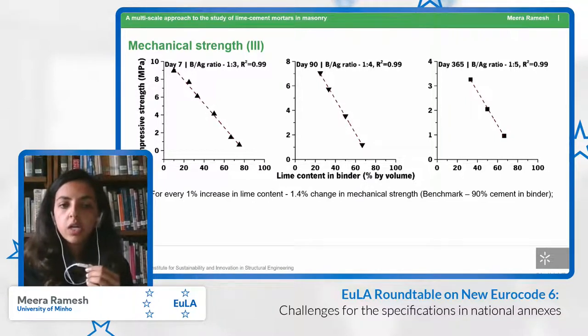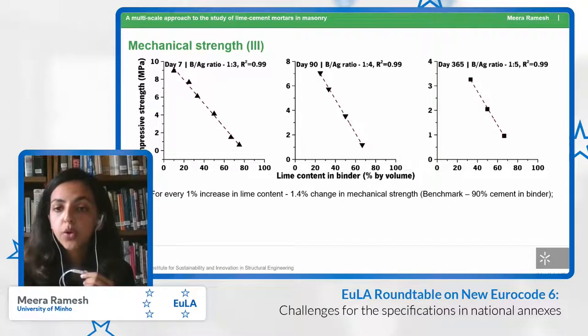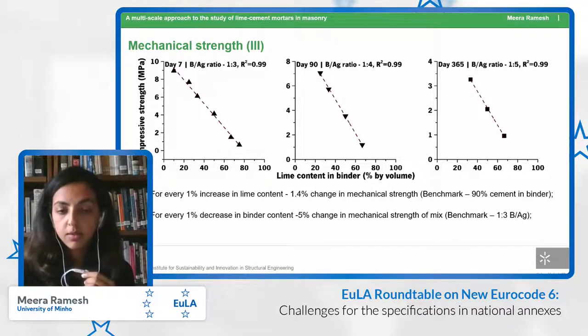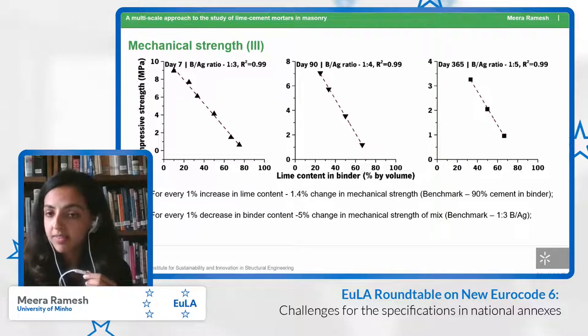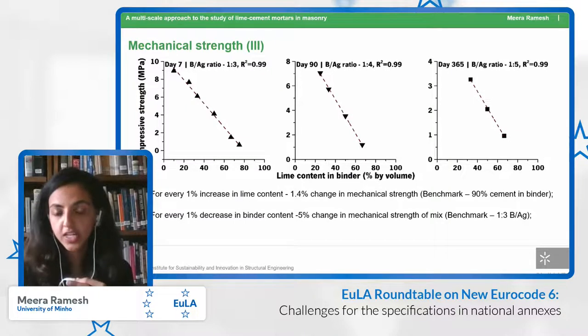So we found out that for every 1% increase in lime content, the change in strength of the mortar is 1.4%. Similarly, for every 1% change in the binder aggregate ratio, there is a 5% change in the mechanical strength of the mix. When I say mechanical strength, I include compression and flexure.